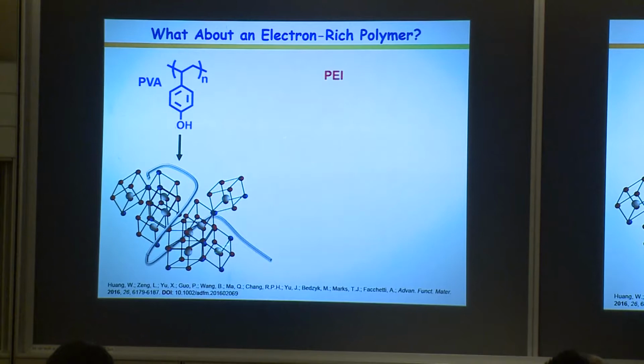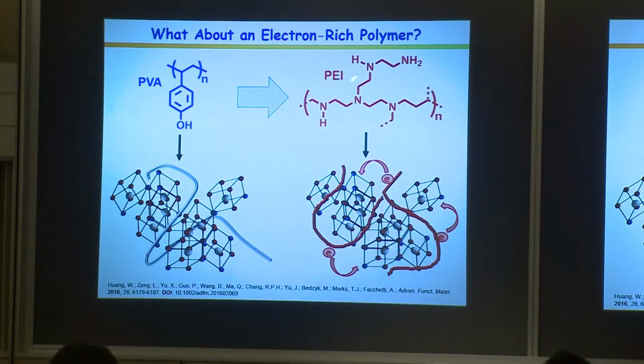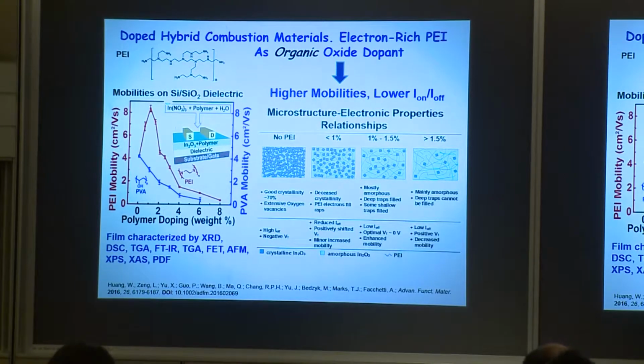So that was polyvinyl phenol, and it works fine. But what we asked, and this is Wei Huang who asked this, was suppose we used a very electron-rich polymer. This is polyethyleneimine, and I'm showing it here. This is sort of a cartoon, but something really remarkable happens. You add a little bit of this to the indium oxide, and the film, spin-coated combustion synthesis, the mobility jumps up. And then it slowly goes down as you add more PEI.